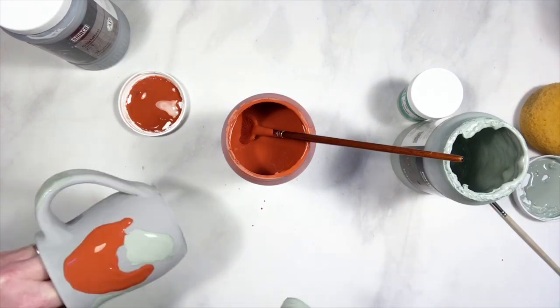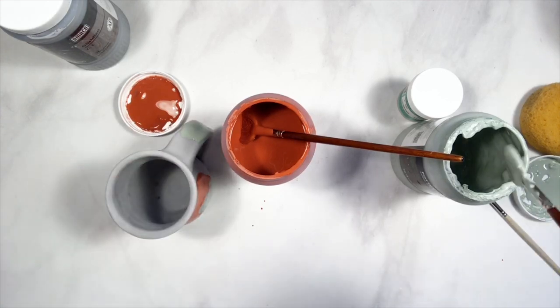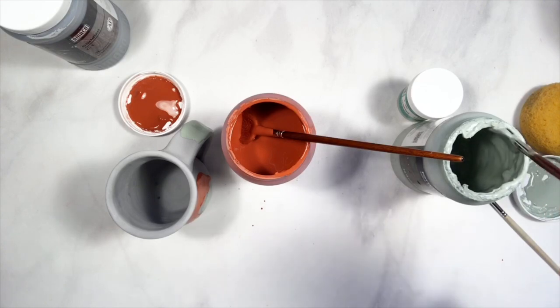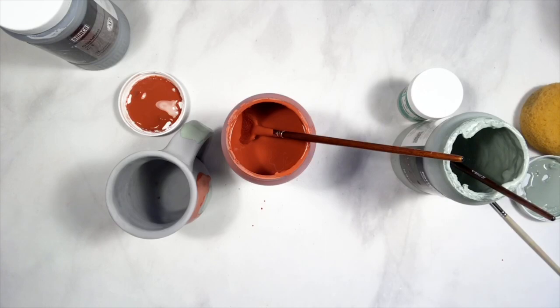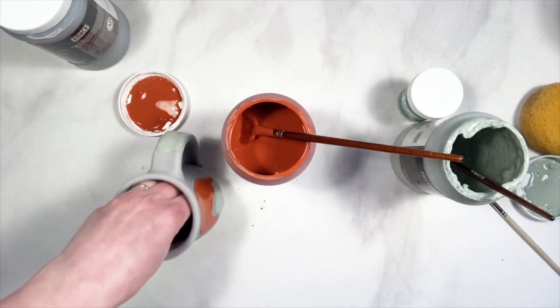You do want to make sure not to get too thick too close to the bottom. Seaweed is always runny — by itself at cone five it may not be runny, but at cone six and applied on top of another glaze it's usually kind of runny. Depending on what you're layering it on, it can be very runny. It will run over the obsidian even though the obsidian is pretty stiff.